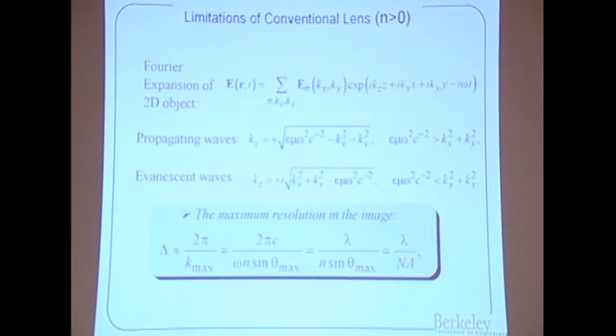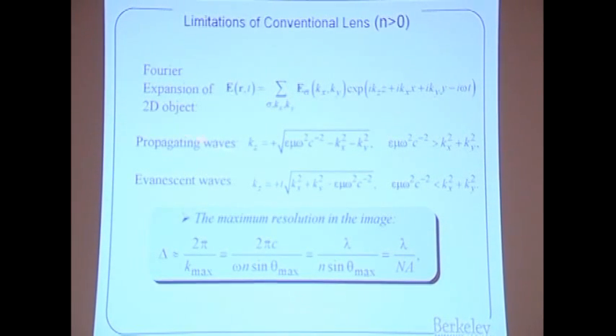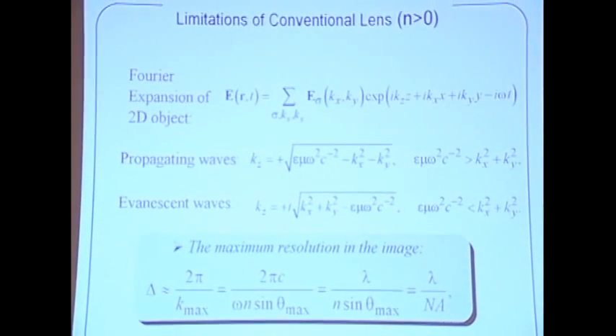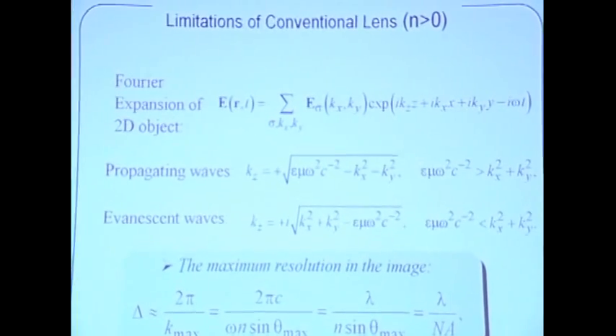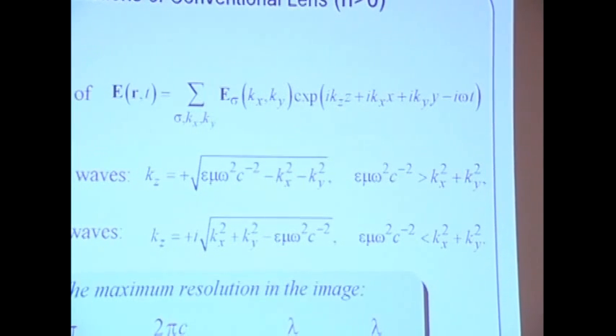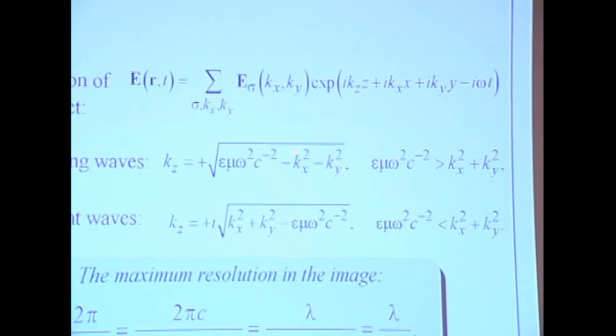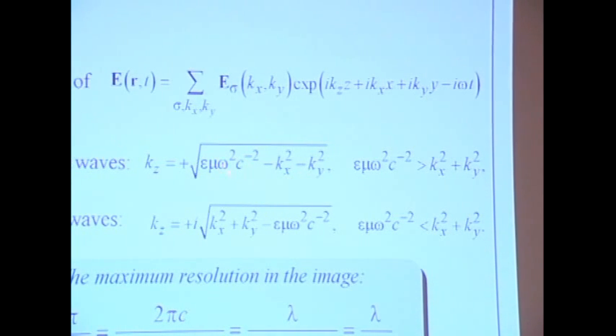We have eyeglasses or lenses you use in the lab. So if you do imaging, essentially, it's a Fourier expansion from object to the image. And you expand that object, the electric component, with a variety of k vectors. And for these k vectors, kz is along the propagation direction, and kx, ky describe the information of this object in the lateral direction. So if the kx, ky squares are relatively small compared to the omega over c term, because momentum has to be conserved, kx squared plus ky squared plus kz squared has to be equal to omega over c squared. So if kx, ky squared is smaller than omega over c squared, kz can be real, so it's a propagating wave. So that can transport this Fourier component from object to the image.